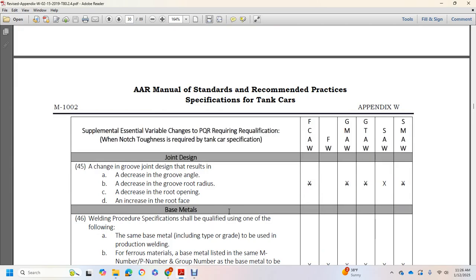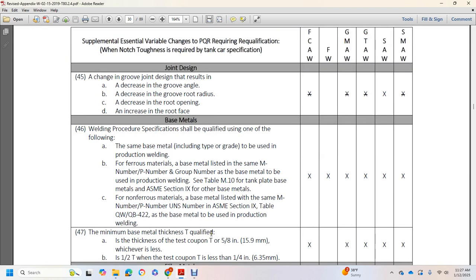45. A change in joint design. A change in groove joint design resulting in decreased groove angle, decreased groove root radius, decreased root opening, or increased root face. Base metal: the welding procedure specification shall be qualified with one of the following: the same base metal including the type or grade to be used in the production weld, or ferrous metal with the base listed in the same M and P number, group number, as the base metal to be used in production welding.